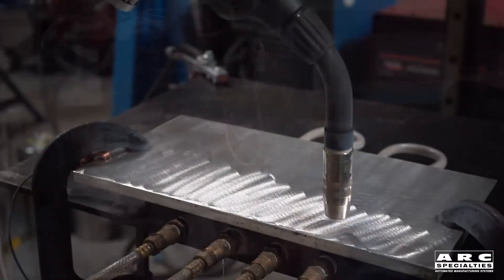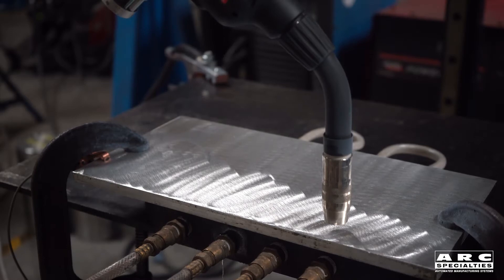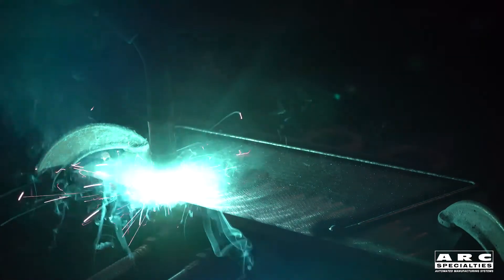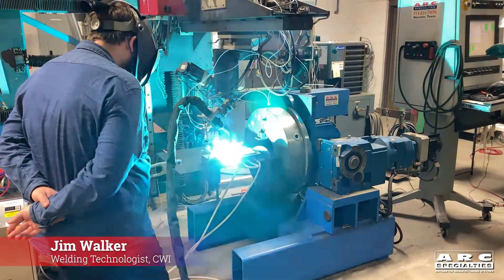In additive manufacturing, this is referred to as WAAM, or Wire Arc Additive Manufacturing. We're using a gas metal arc welding process. You can tell that we have a water-cooled platen underneath the part to try to maintain interpass temperatures, and you're going to see a time-lapse photography of us building an eight and a half pound part in under three hours.